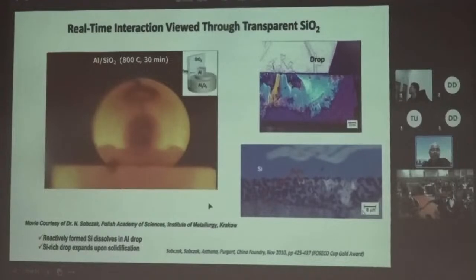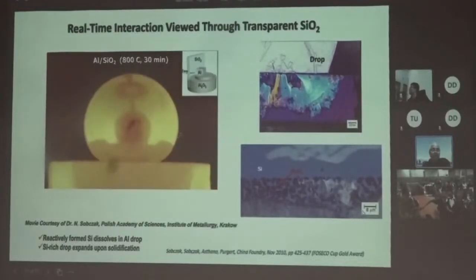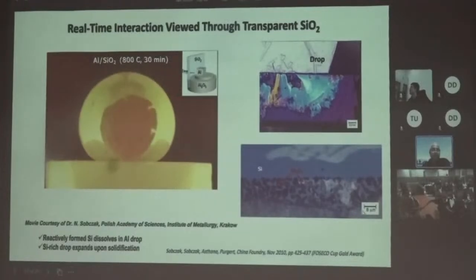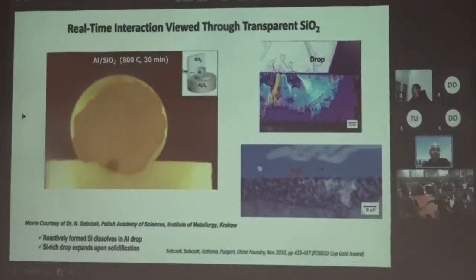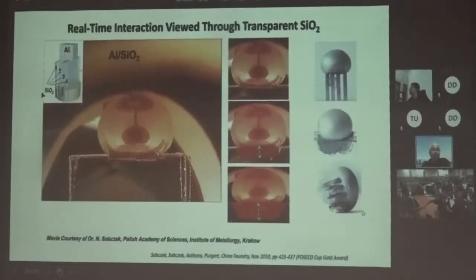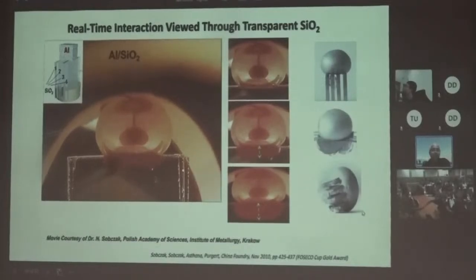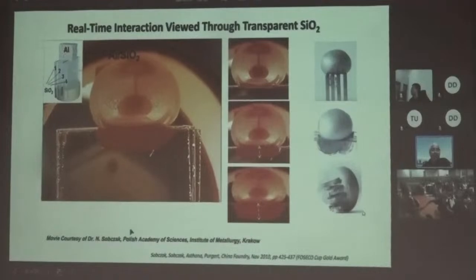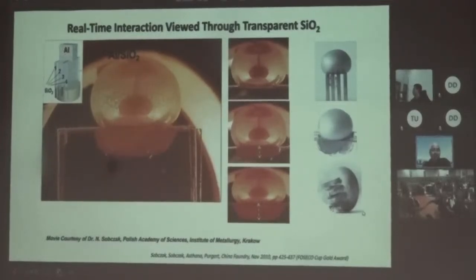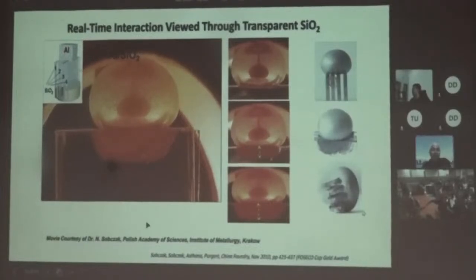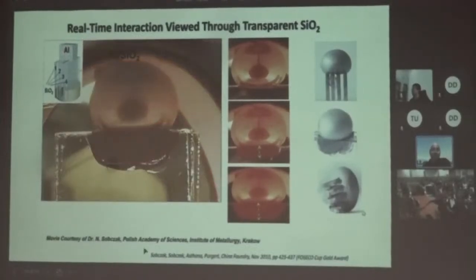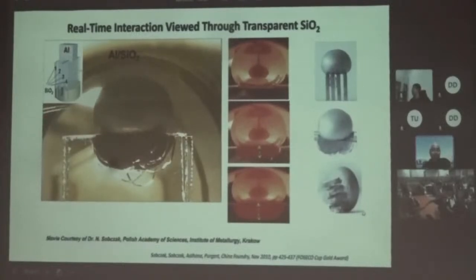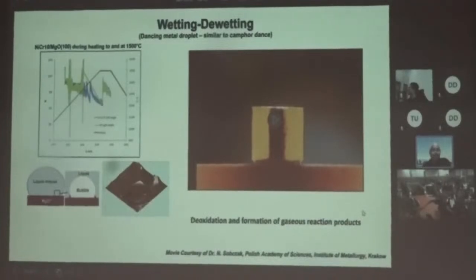Here you're looking at the real-time reaction between aluminum and silica. This is the silica plate, and you're seeing the reaction layer forming through the transparent silica substrate. You can study in situ the interactions that are taking place. Here, you're looking at several silica plates through which liquid aluminum is permeating and also reacting. The liquid is moving, the reaction layer is forming, so you can see the kinetics of spreading and the kinetics of reaction from this kind of system. A lot of things are happening that we don't see without this kind of instrument.